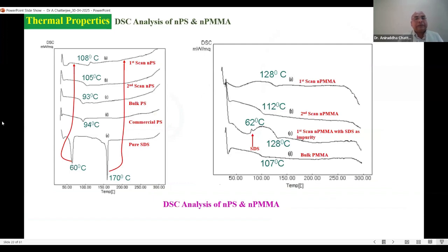So here you can see basically the melting temperature of pure sodium dodecyl sulfate at 60 degrees and 170 degrees. These are the two melting peaks basically present in pure SDS, and this is the glass transition temperature of commercial PS, that is 94. For bulk PS it is 93, and for pure polystyrene nanoparticles it is 108, where the second scanning shows 105. So if you compare the glass transition temperature of bulk and commercial PS with nanoparticles, then there is a hike of glass transition temperature.